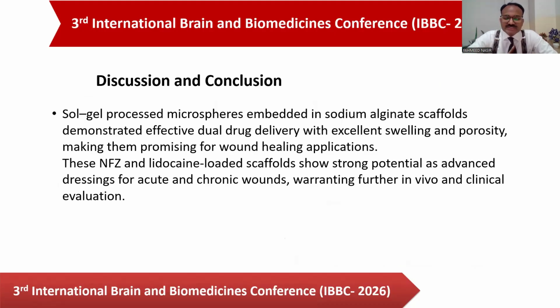And in conclusion, sol gel processed microspheres embedded in sodium alginate scaffold demonstrated effective dual drug delivery with excellent swelling and porosity, making them promising for wound healing applications. These nitrofurazone and lidocaine-loaded scaffolds show strong potential as advanced dressings for acute and chronic wounds, warranting further in vivo and clinical evaluation, as I performed only the in vitro study for the scaffold.